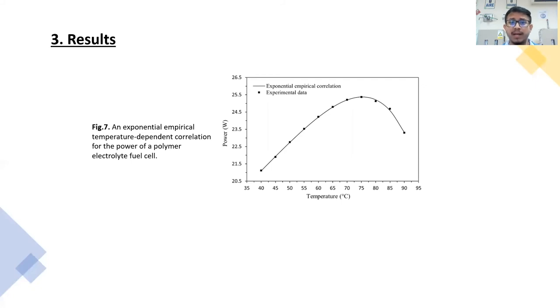This provides evidence that high proton conductivity doesn't necessarily mean higher output power. There are other factors that can affect the performance of PEFCs, such as the electrochemical platinum surface area, which is a measure of hydrogen absorption in catalyst layers. Also, water management within the polymer electrolyte fuel cell must be carefully considered. The maximum power obtained was 25.4 watts, obtained at 75 degrees Celsius, with a conductivity of 73 millisiemens per centimeter.